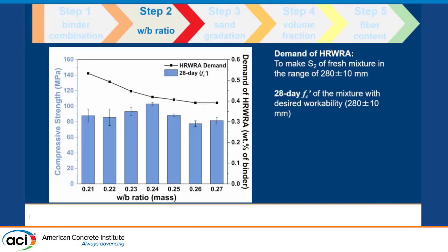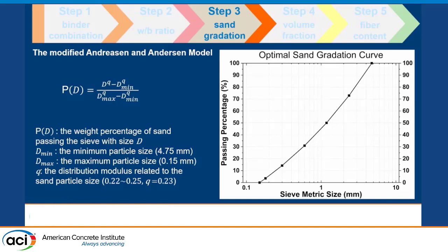Now we're going to move on to step 2, which is to determine the water to binder ratio. We will use the obtained optimal binder combination with various water to binder ratios to test their 28-day compressive strength and the demand of high range water reducer in the mixture to achieve the flow diameter of 280 plus or minus 10 millimeters. According to the results, we can say that the optimal water to binder ratio is 0.24.